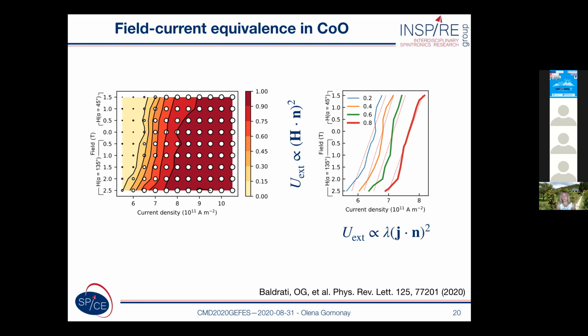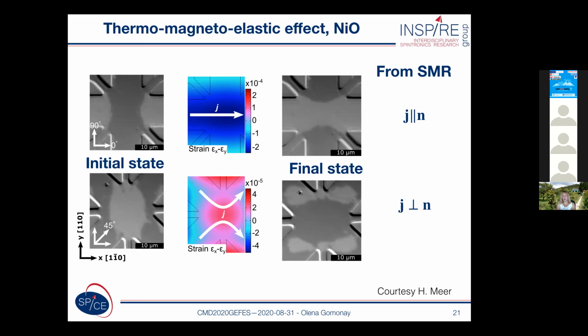lambda, which can be different for different materials, but it also depends on the geometry of the electrodes. So in order to disentangle the effects of spin-orbit coupling or electromigration from the thermomagnetoelastic mechanism, the easiest way is to compare materials with different magnetoelastic constants and the same material with different geometry of the current flowing through the system. And this is what was recently done in our group, in Matthias' group, with which I collaborate.